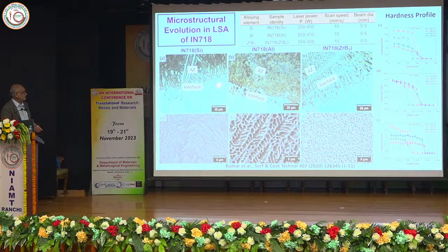What is even more significant here is this interface. You see, this is completely superalloy, and this is where you're gradually changing. They grow epitaxially, near epitaxially, with a certain direction rate. Most important, there's no crack - there's absolutely no decohesion, because you're starting with a metal and gradually changing your composition and making it intermetallic.